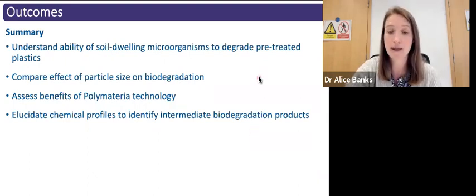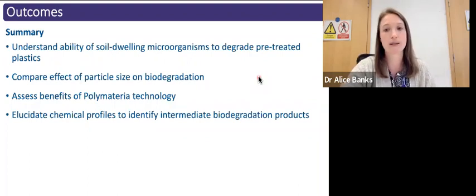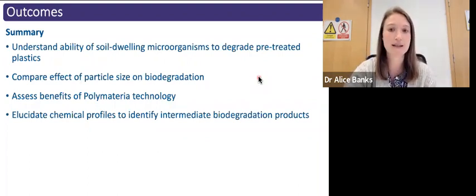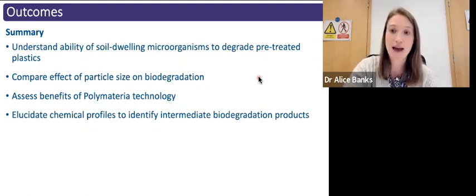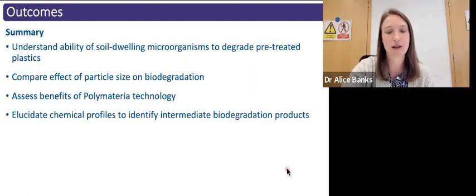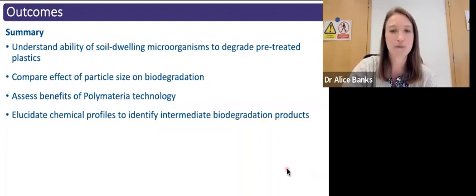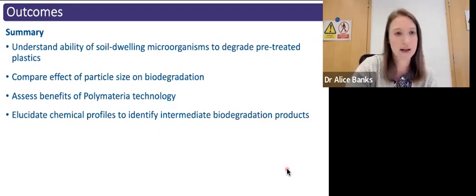This initial polyethylene experiment will also help us to see whether or not the particle size has an effect on the ease or the speed of degradation. And we'll also gain an understanding of the benefits of including the Polymateria technology and whether that aids the speed of degradation. And finally, the chemical profiling is going to provide an indication of the intermediate products that are formed, and this will inform us of the likely metabolic pathways which are responsible for the activity that we see.